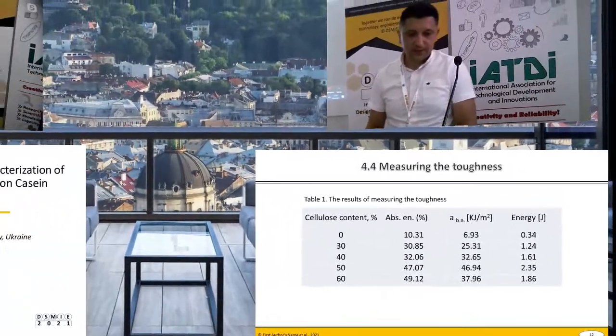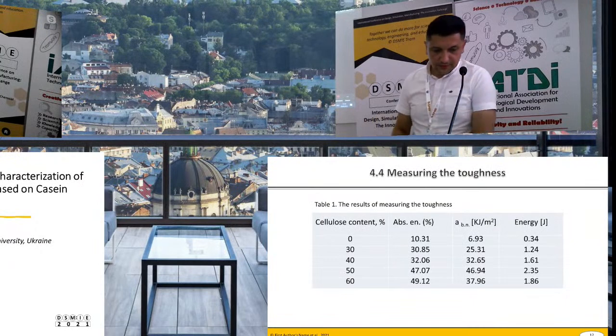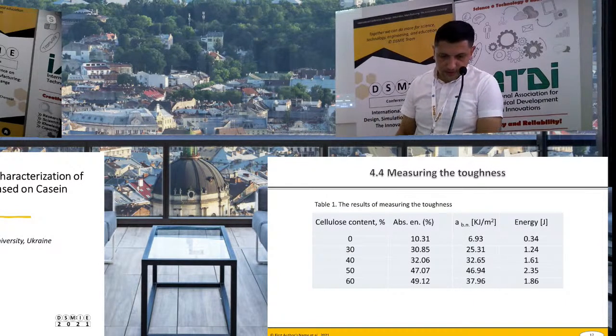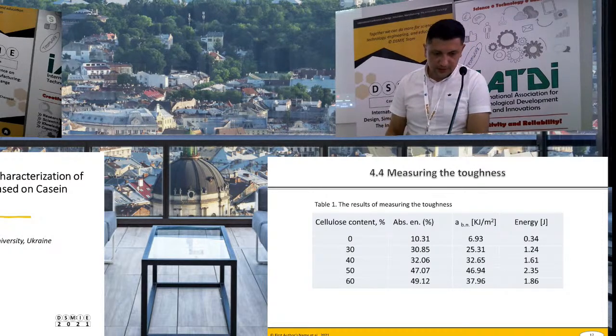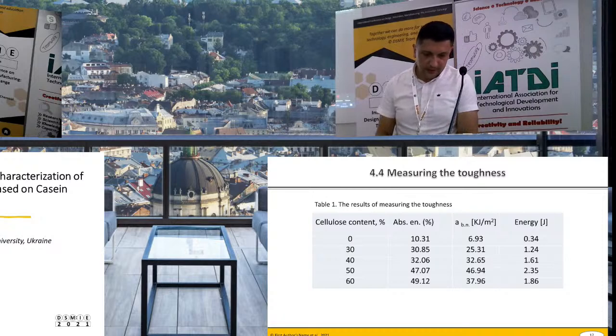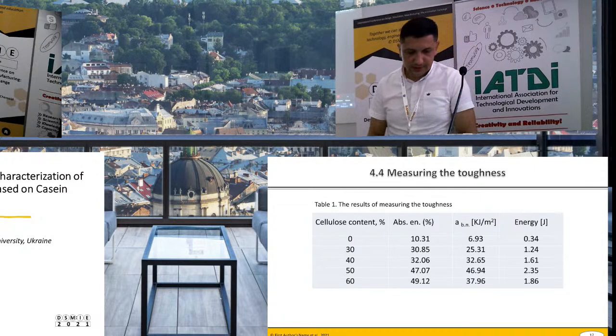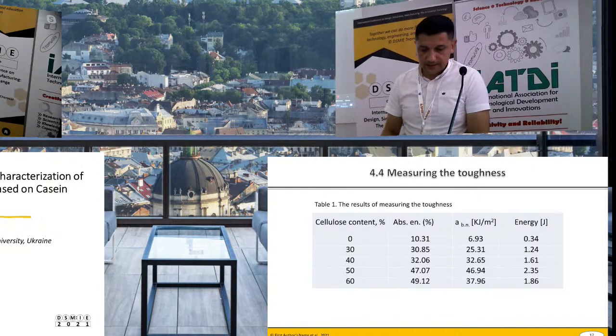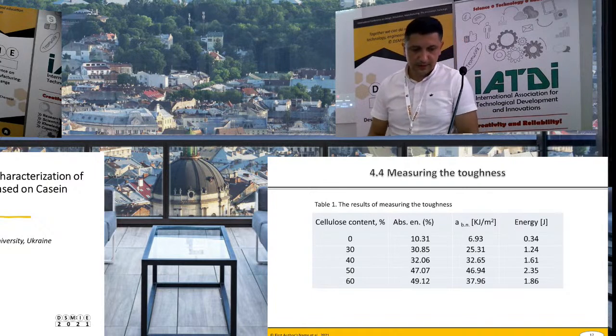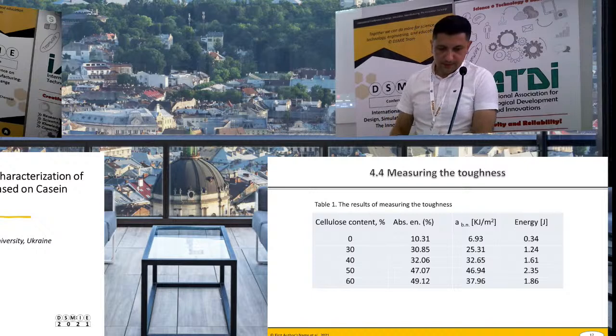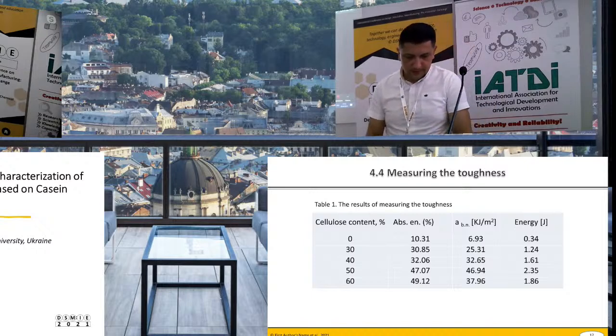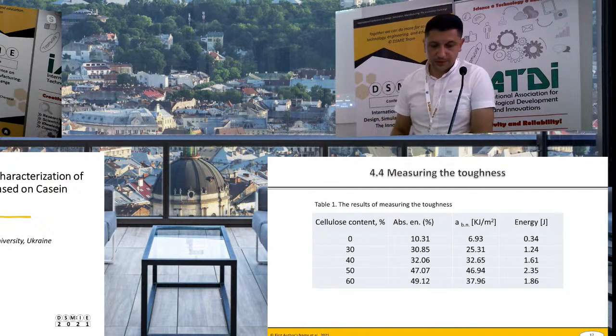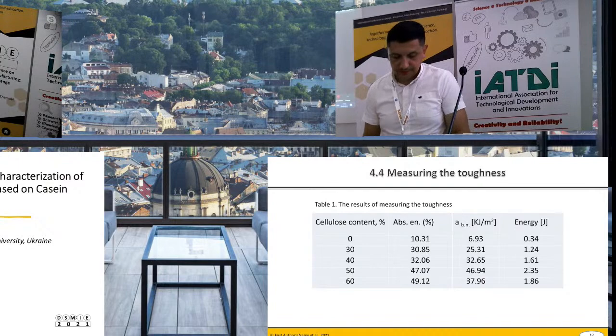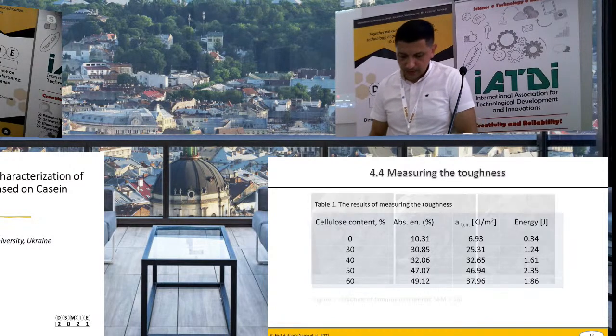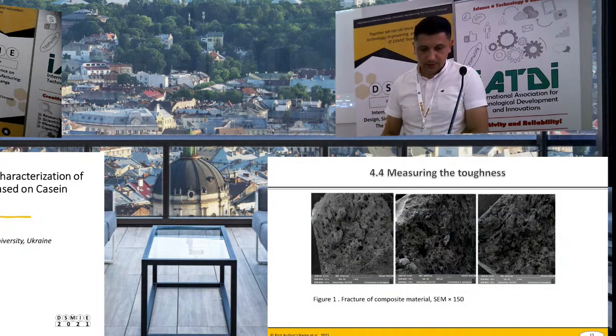It's the result of measuring the toughness. We can see on this slide the energy and absorbed energy in kilojoules per square meter, the toughness, for the other samples which include other cellulose content. The best result was shown by samples which include 50% microcellulose in the matrix. Please, next slide.